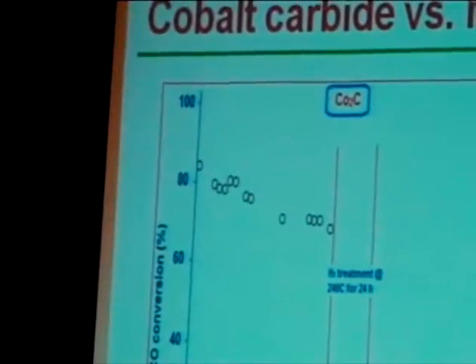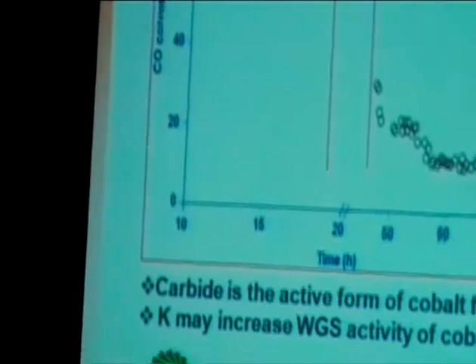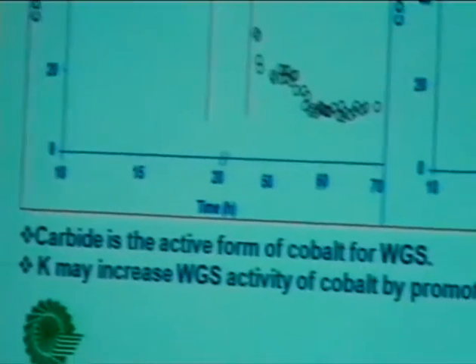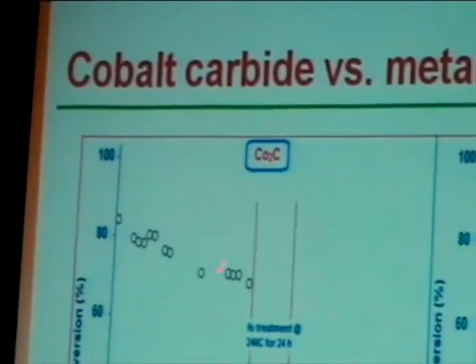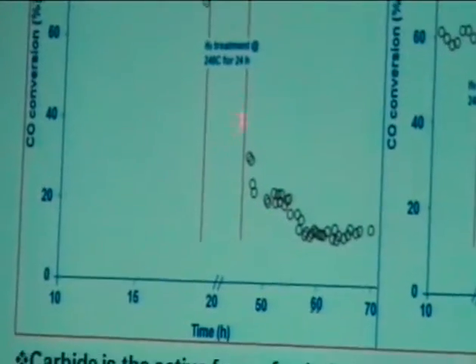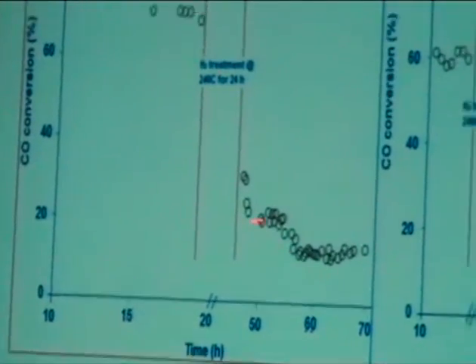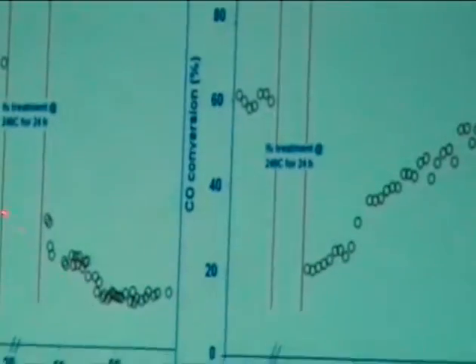And in order to confirm further the effect of potassium in this case, what we did was take the cobalt carbide, run the water gas shift under certain conditions, and then we discontinued the water gas shift and did a hydrogen treatment. As you see, after the hydrogen treatment at 240 for 24 hours, the water gas shift activity dropped, and then it stays constant. Whereas in the case of potassium, the activity dropped and then it keeps increasing with time.